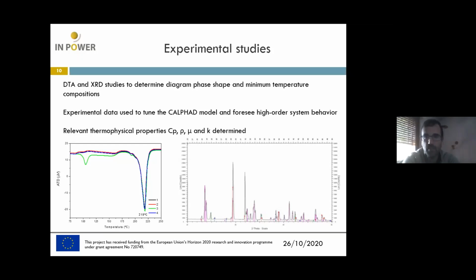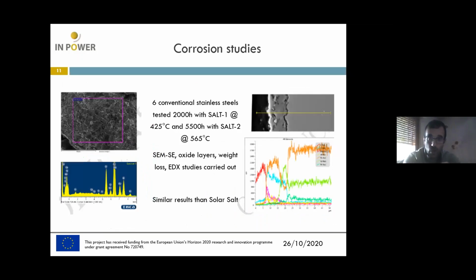Other thermophysical properties, so to speak, Cp, density, viscosity, and thermal conductivity were determined by experimental means. Also, talking about corrosion studies, the addition of new components to the system can be tricky, because these new components can be more corrosive or harder on the conventional materials used in this technology. So we tested about 2,000 hours with one of the compositions at 425°C, and almost 5,500 hours with the other composition at high temperature, to test 6 different conventional steels.